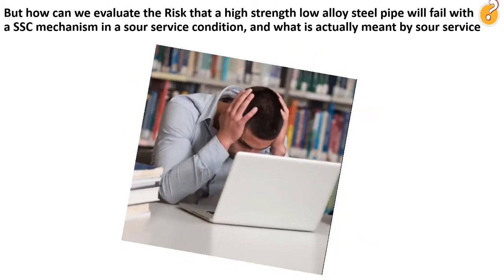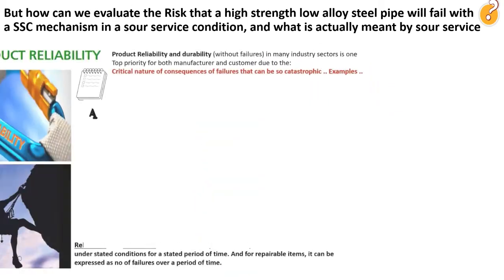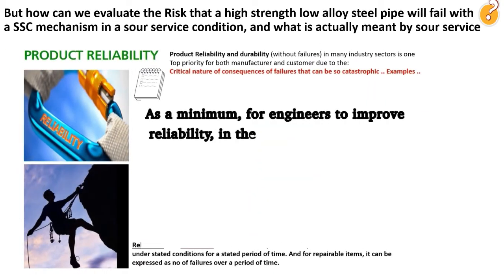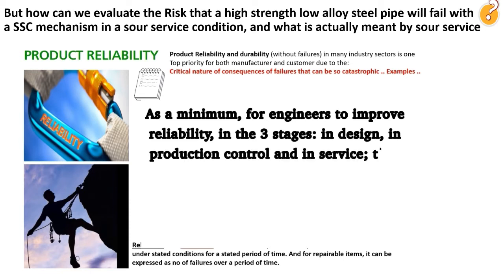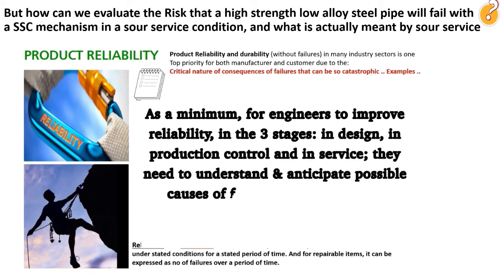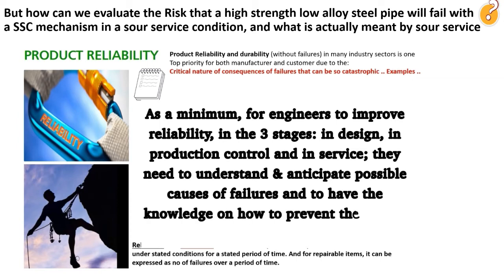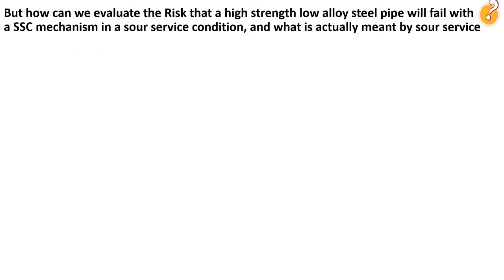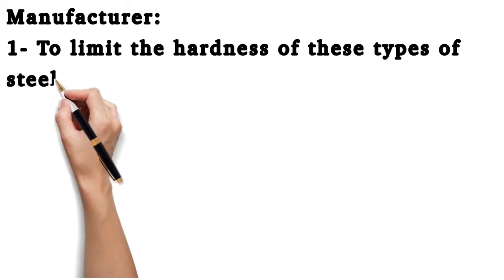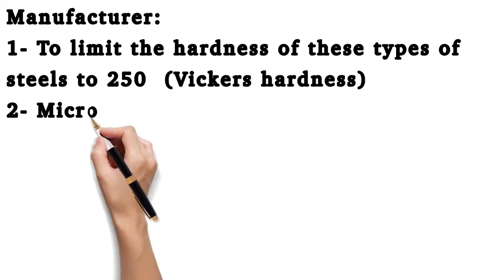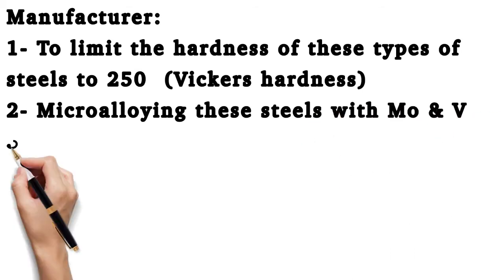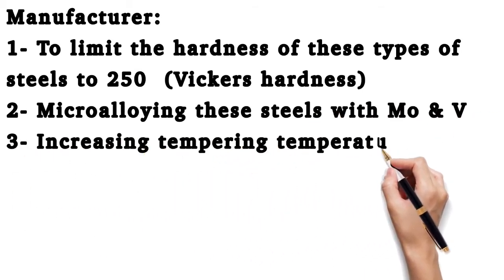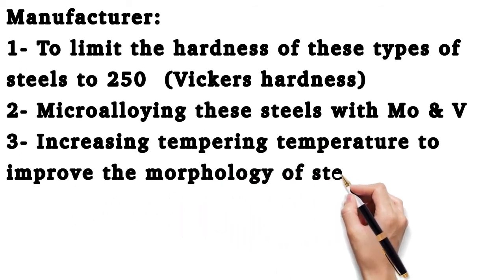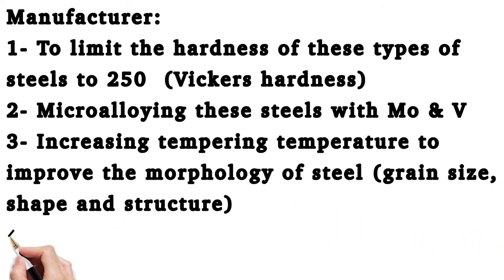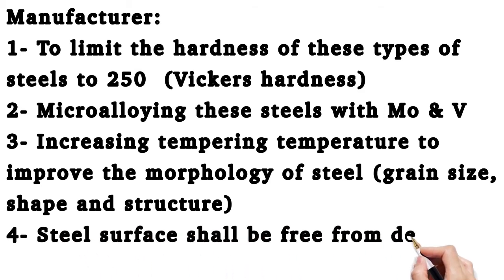Now, after this quite complex part, let's try to apply what we learned in the last part about reliability. In order to reduce the risk of failure by SSC, the manufacturer can reduce the probability by increasing product engineering reliability as follows. First, since high-strength steels are more susceptible to SSC than low-strength steels, it is a common industry standard to limit the hardness of these types of steels to 250 Vickers hardness. Then, microalloying these steels with molybdenum and vanadium, and increasing the tempering temperature to improve the morphology of the steel: grain size, shape and structure. The steel surface shall be free from defects or stress risers.